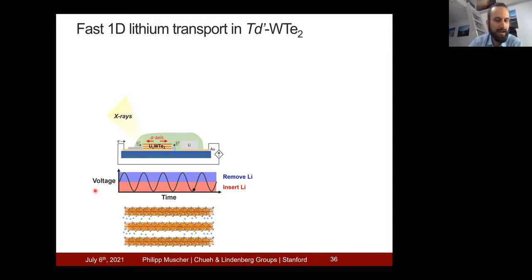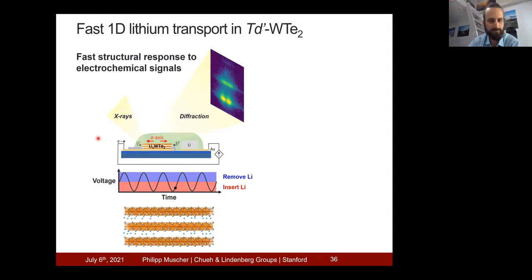And then I can use X-rays to look at this edge of the sample and see how it is evolving over time using X-ray diffraction. And you can see that a fast structural response follows the fast electrochemical signal that we're feeding into the system.